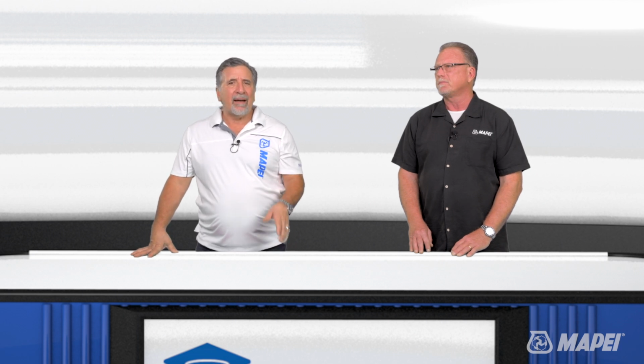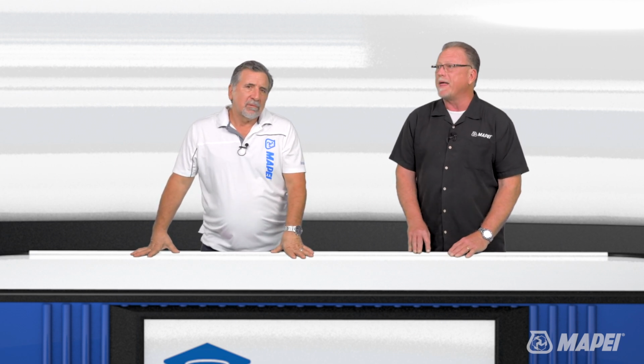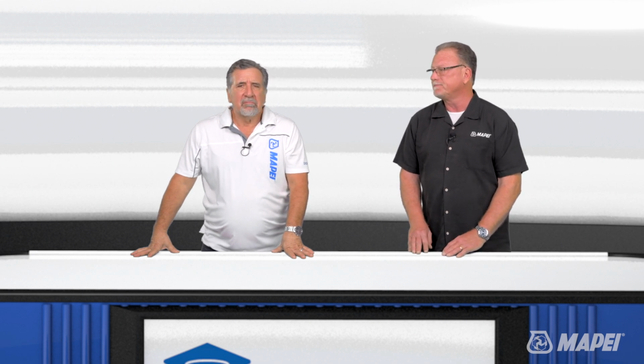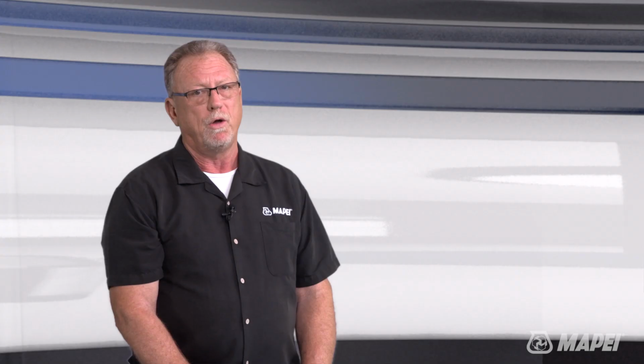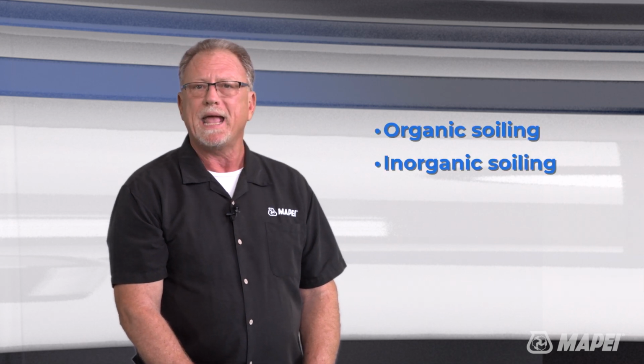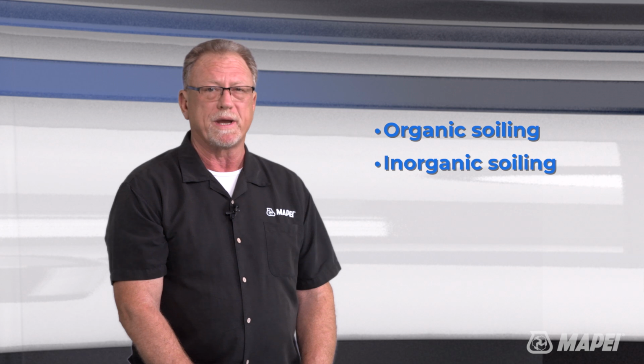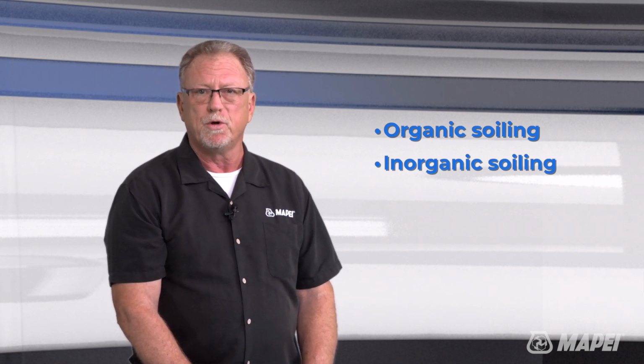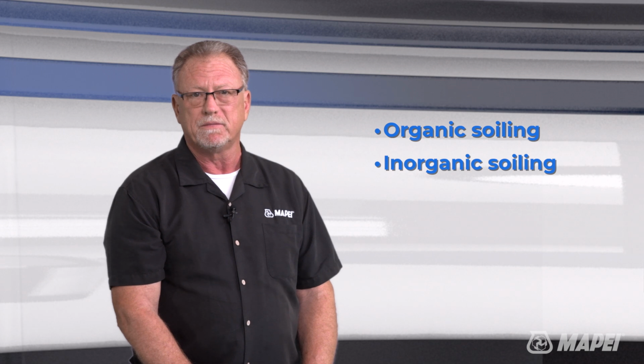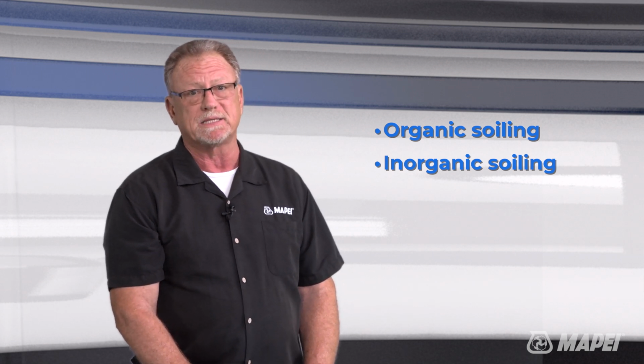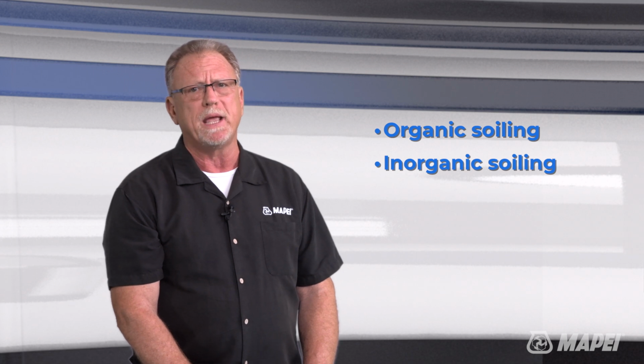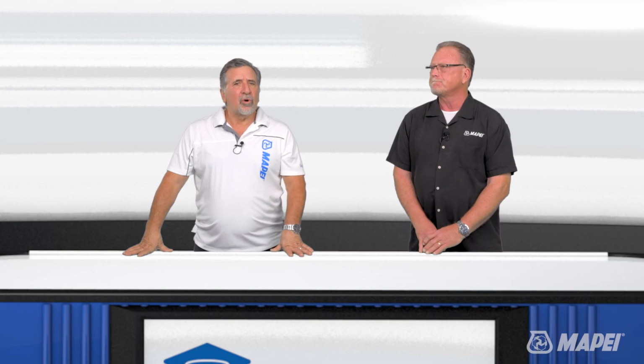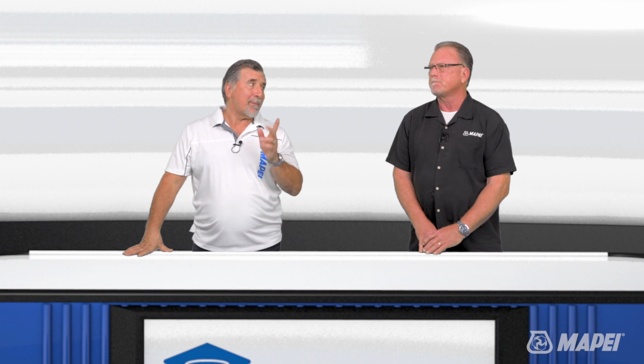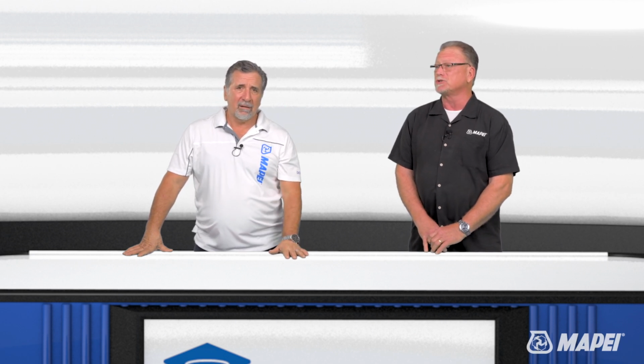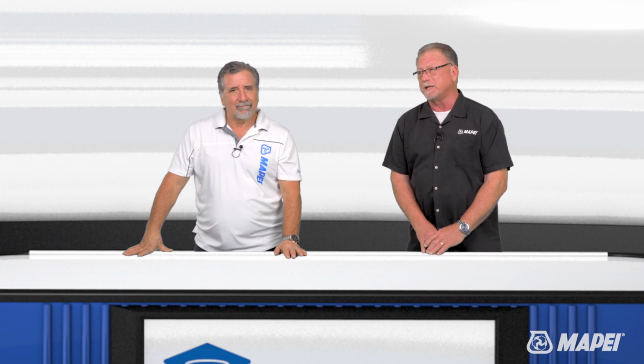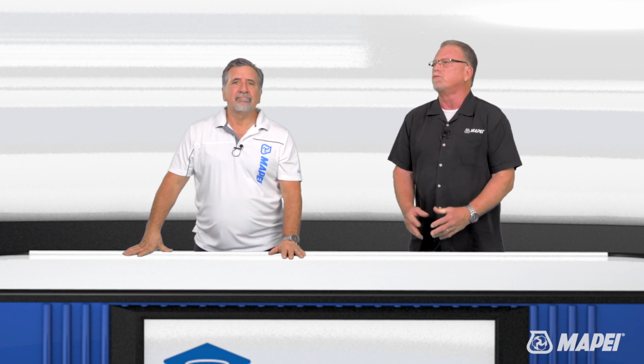So what do we do if we have a really dirty surface? Well, that depends on the type of soiling that we are removing. What do you mean by the type of soiling? Well, there are two types of soilings, organic and inorganic. Organic soiling is dirt, grease, and grime. Organic stains are best removed using a high pH alkaline cleaner. And for inorganic soils, such as efflorescence or hard water spots, using a low pH acidic cleaner is recommended. So knowing which type of soil you have saves you time and money. Yes, because alkaline cleaners don't remove efflorescence and acidic cleaners don't remove grease and oil. So you won't waste time using the wrong products.